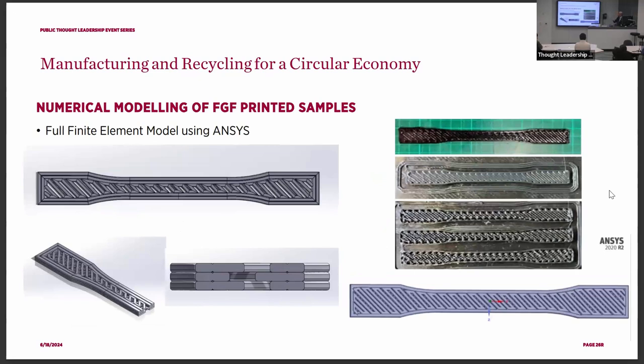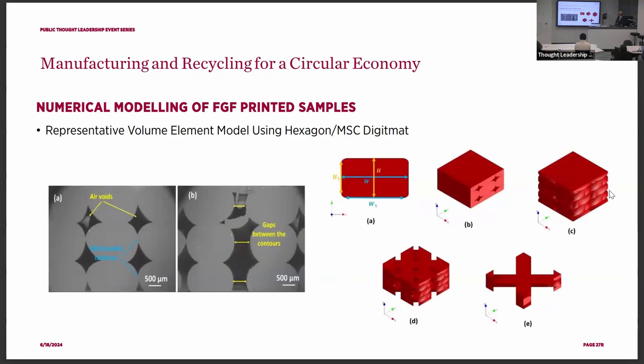And as I mentioned, we did a finite element model for both the full model and the RVE model. This full model is a bit complex. You can see that it's a three layer model, and it's a cross section. You can see what we developed to make the full model available. And then we do the testing. You can see the printed structures, the samples. On the top is for PC, polycarbonate, and at the bottom is all for the PETG, the white color.